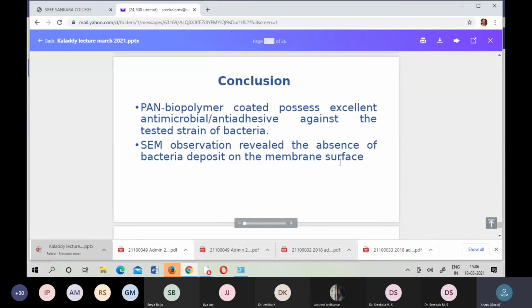The similar thing we tried with the other biopolymers too, but we didn't publish the data. I think it's under revision in some cases. So the other kinds of biopolymers can also be utilized, but only under certain conditions, because generally biopolymers are highly viscous in nature. So we shouldn't spoil the membrane surface. We shouldn't block the pores. We have to retain the surface and cross section, but we have to add, like, a thin layer of cheese or something on your bread. Make sure the thin layer exists, but without spoiling the background, the remaining polymer. We can use these biopolymers to a certain extent to control fouling.